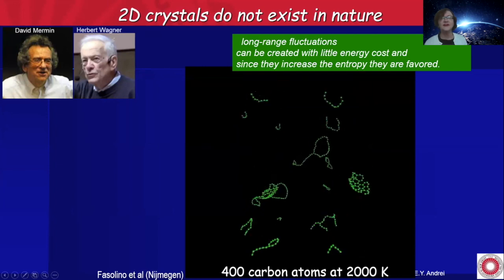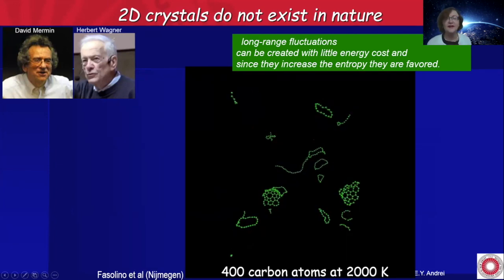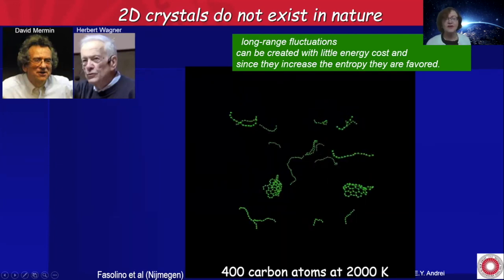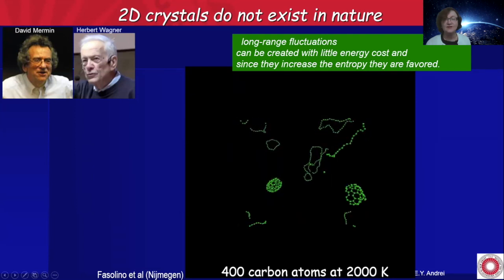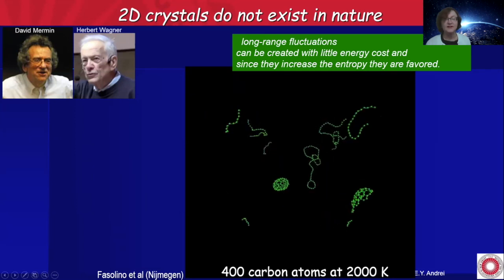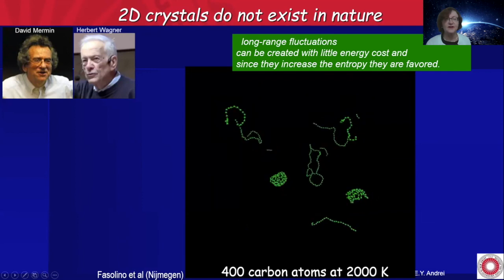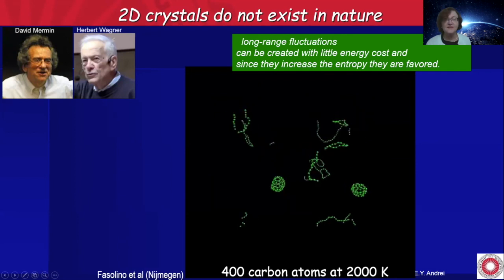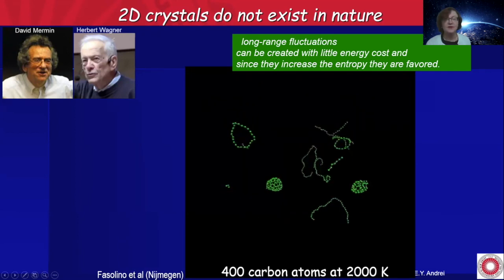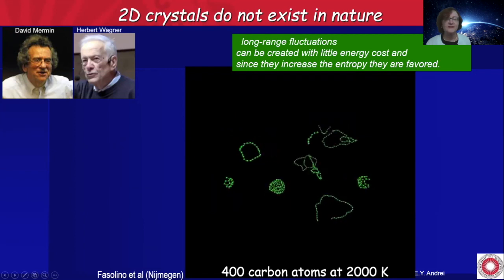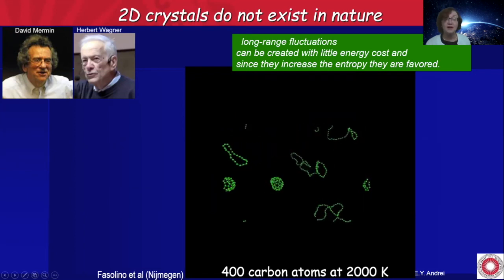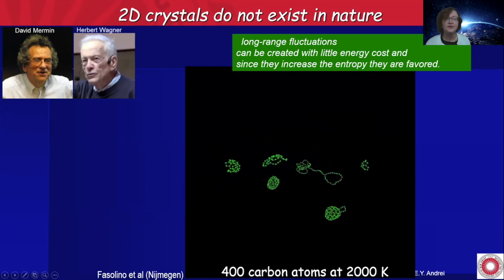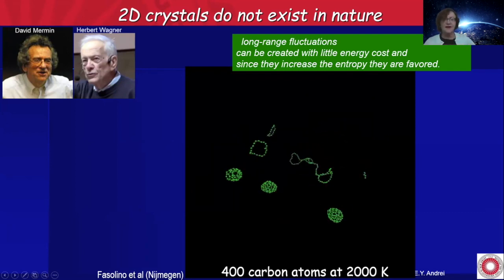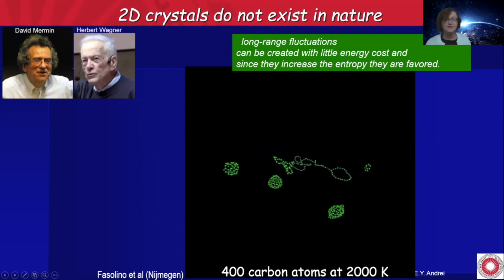and you digitally heat them up to 2000 Kelvin and you watch what happens. And what you see is they have very large fluctuations due to the temperature, and sometimes they will form what's called a buckyball here, they form rings. But no matter how long you'll be waiting, you cannot form a two-dimensional crystal. And that is because the fluctuations are so cheap, it never gets to form a sheet.